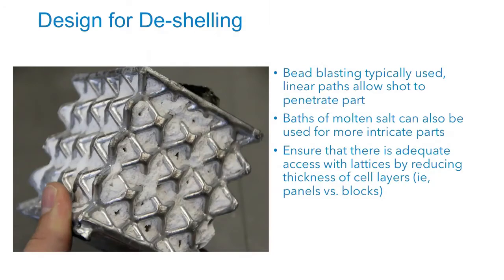Another important aspect is designing for deshelling. This is a lattice cube that still looks like this under my desk, because after an hour and a half in the sandblaster, we weren't able to get the shell out of that. So you want to think about how you're going to get the shell out of your parts. You want to think about lines of sight, because you're going to be using generally high velocity abrasive media or water jets to get it out. So you want to make sure that you can see every piece of the shell that you want to abrade.